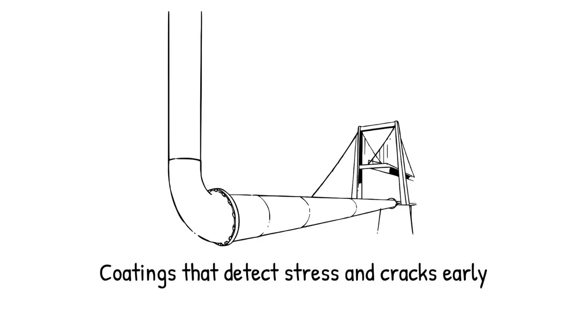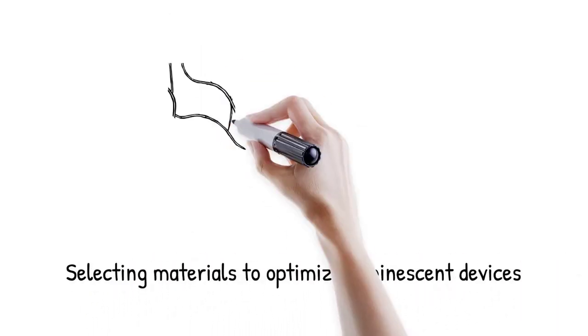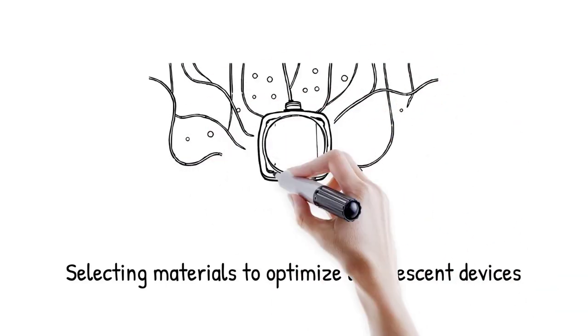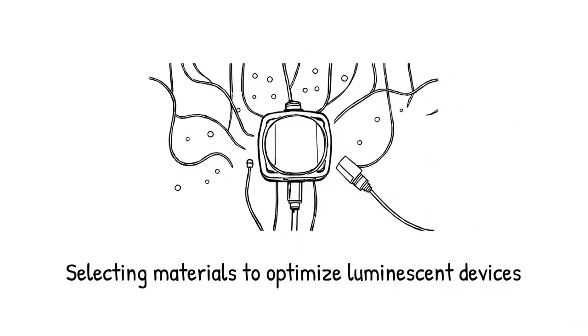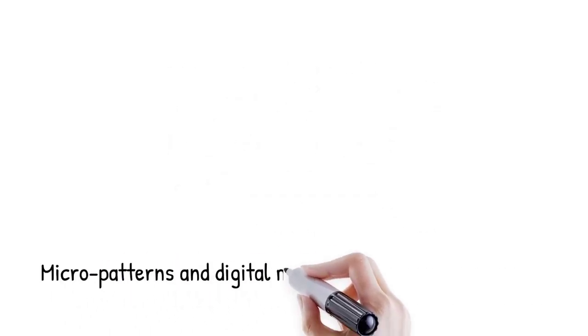Embedding blue-doped CaSnO3 particles in a polymer matrix allowed crack detection under tensile stress via visible blue flashes. It's like coating a bridge with paint that lights up where cracks form. Spotting damage before it worsens. Engineering devices require selecting host crystals, dopants, and matrix materials that optimize photon yield, color, and mechanical compatibility. Composite films often mix triboluminescent powders with elastomers to combine flexibility and luminescent response. Micropatterning techniques create pixelated arrays for spatially resolved stress mapping.